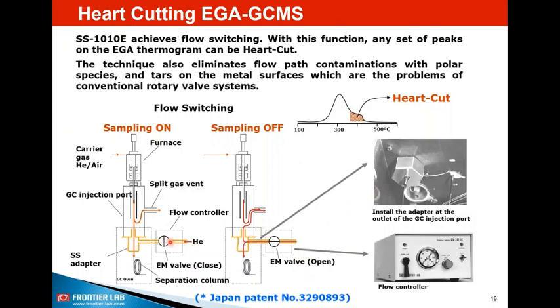The Selective Sampler has a valve and also additional carrier gas. When the sampling is on, this valve is closed, so your sample can reach the GC column directly. When the sampling is off, you get the helium gas flow from this selective sampler, and it will have a flow split that will push upward to ensure that nothing from the sample reaches the column, so no interference. So this is how this valve and additional gas line help to fraction the zone that you are interested in analyzing by heart cut.